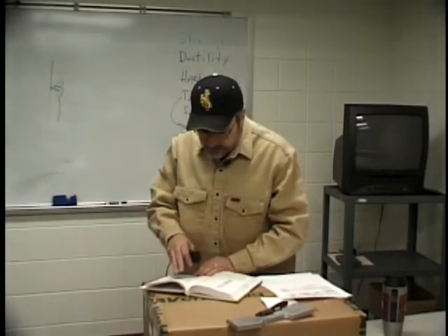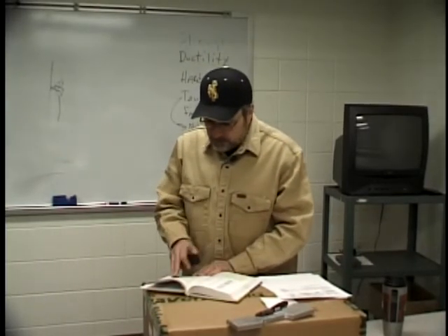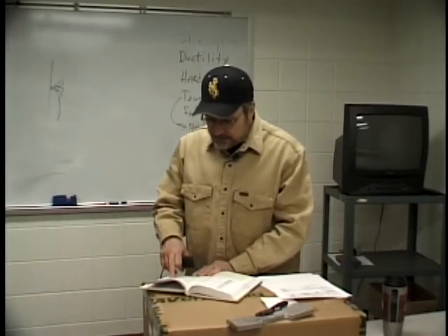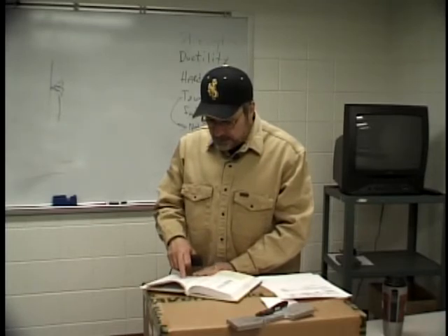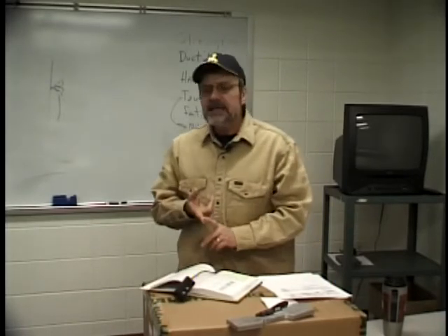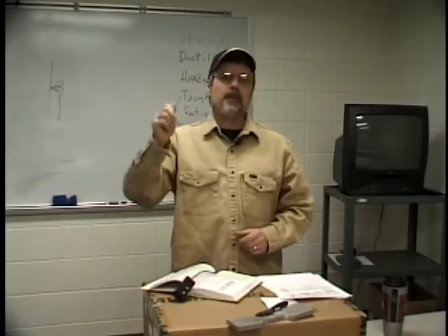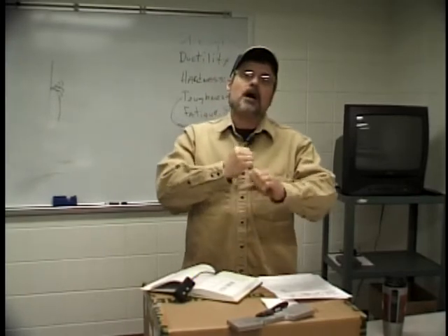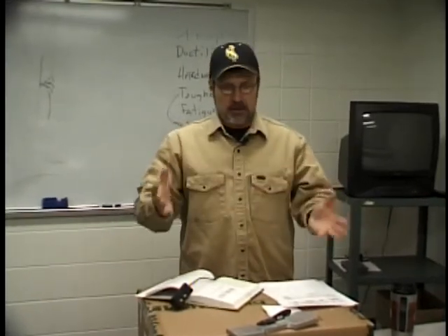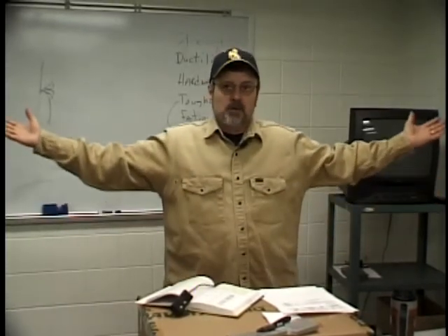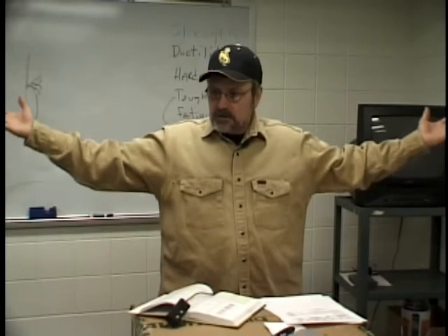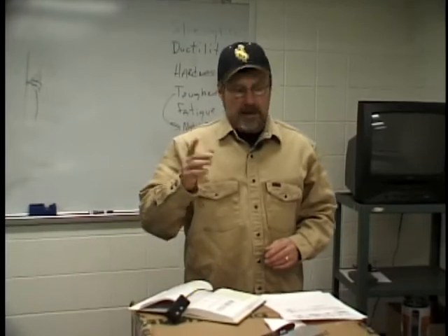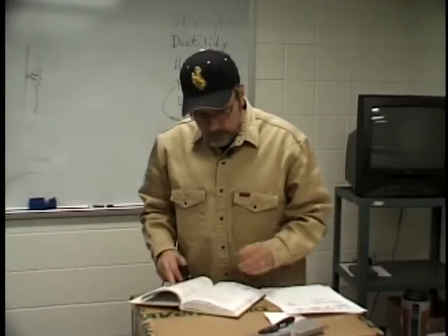I showed my slides, and we talked about it a little bit. If you go to the second paragraph, highlight the last sentence where it says residual stresses can be relieved by heat treatment, by physically removing a section of the metal, or by yielding, that is distortion of the weld metal. You can peen it. I'm not talking about taking a chipping hammer and going pop, pop, pop, but vibratory stress relieving, they call it. You really get on it, and you can relieve some of those stresses that are built up in that manner. Allowing it to give will release some of the stresses, or more commonly, you will stress relieve it by post-weld heat treating it. PWHT is how it's abbreviated.